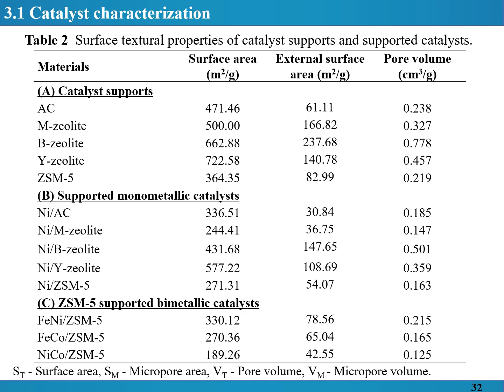In relation to the catalyst supports, including the activated carbon and zeolites, the supported monometallic and bimetallic catalysts exhibited a relatively lower surface area and pore volume, following the occupancy of their pores by the active metal dopants.